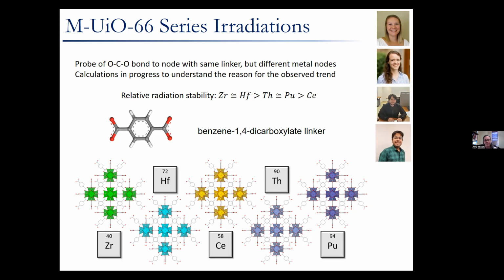Right now what we can say is that the radiation stability follows this trend. The zirconium and hafnium MOFs are roughly of the same stability and are slightly more stable than thorium and plutonium, which are more stable than cerium. Right now we're completely at a loss as to how to explain this. It doesn't follow any trend that we would have expected. So it's something that we're working with our computational colleagues to try to understand.